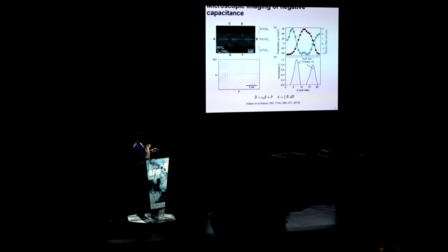But what we could also do with David Muller's group at Cornell is to map out the electric field in the system. The way they do it is that if there is an internal electric field in a material, you send in an electron beam, and it gets deflected. By using a very, very sensitive detector, they can then say what the electric field looks like inside the material. Again, these are very recent developments and very exciting, because we used to say a built-in electric field you cannot measure, but actually people can image it now.